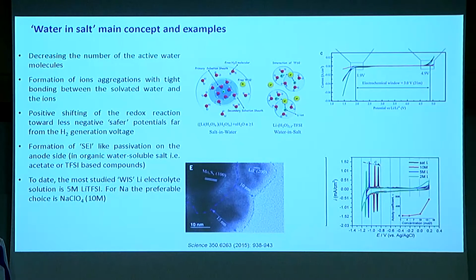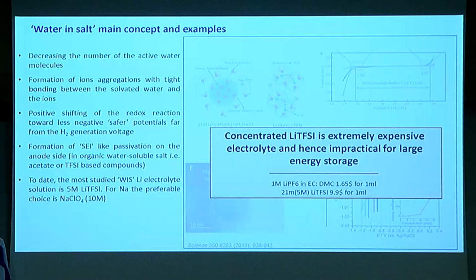So the most studied water-in-salt, at least for lithium electrolyte, is the 5 molar or 21 molar lithium TFSI. For sodium, for example, there is a sodium perchlorate salt, which in a concentration of 10 molar. But speaking about lithium TFSI, it's completely impractical because you can see here it's extremely expensive electrolyte, and I just made some rough calculation. You can see here lithium hexafluorophosphate, the conventional electrolyte for lithium-ion battery, it's about $1.6 per 1 ml, while lithium TFSI is about $10 per 1 ml, so clearly it's not practical